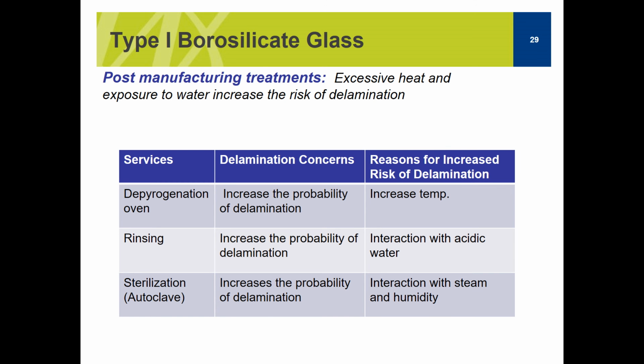Okay, now this is great. So we talked about coating, we talked about manufacturing processes, and we talked about the chemical composition. But if we are targeting the parenteral market, we're going to take these vials, and these vials have to go through post-manufacture treatment. They're going to have to go through a depyrogenation oven, they're going to have to be rinsed, and they're going to have to be sterilized or autoclaved. Okay, and I'm not going to talk in too much detail about what happens to that glass vial after these steps, but there's a general rule, a general sense, that every time you take the vial and expose it to heat or water, you increase the risk of delamination.